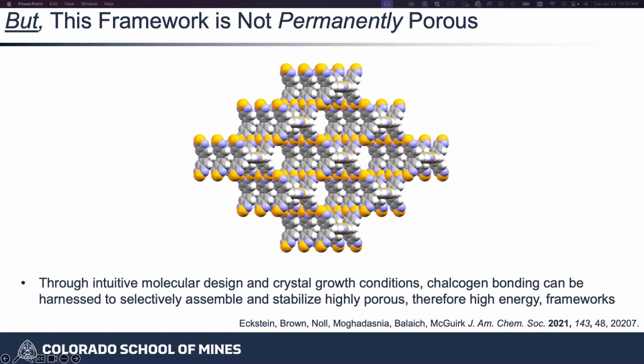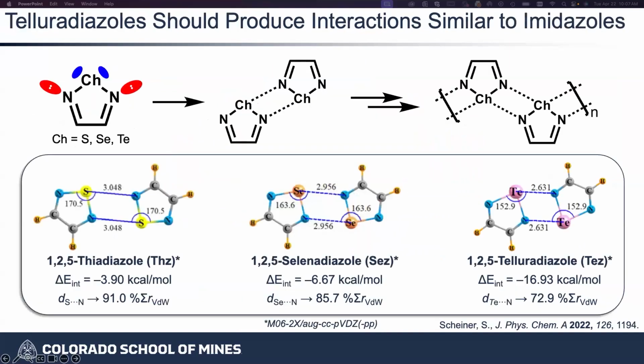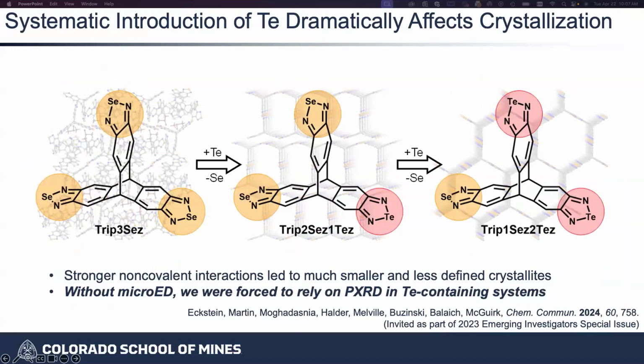And so what we've been doing, this is a few years ago now, the journey that we've been going on is getting to tellurium, because very clearly when you go from selenium to tellurium, you're going to make that structure much more robust. And so we published a paper last year where we were making these hybrid systems. And again, this is just because of the synthetic challenges of using tellurium. But in this case, we were going from systems with selenium where we're getting these huge fat single crystals, massive single crystals. And every time we introduce more and more tellurium, we're getting smaller and smaller crystallites.